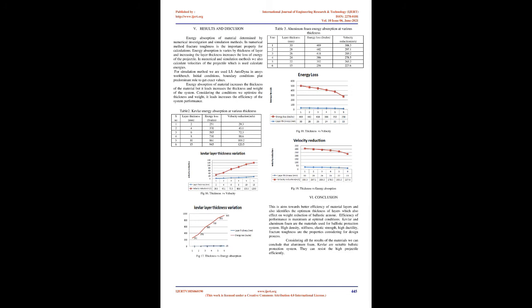Conclusion: this work aims towards better efficiency of material layers and also identifies the optimum thickness of layers, which also affects weight reduction of ballistic armor. Efficiency of performance is maximum at optimal conditions. Kevlar and aluminum foam are the materials used for the ballistic protection system. High density, stiffness, elastic strength, high ductility, and fracture toughness are the properties considered for the design process. Considering all the results, we can conclude that aluminum foam and Kevlar are suitable for ballistic protection systems. They can resist high-speed projectiles efficiently.